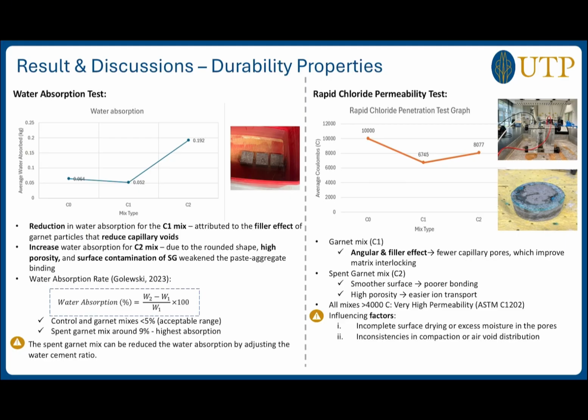The same trend was observed for RCPT, where the garnet mix has reduced chloride penetration compared to control concrete. It is because of the angular shape and filler effect, which can promote fewer capillary pores and improve matrix interlocking. And the spent garnet has increased chloride penetration because the smoother surface can lead to poor bonding, and it can make ions transfer easily. So, even though there is a reduction in chloride penetration for spent garnet and garnet mix, these two mixes are categorized under very high permeability because the charge passed is higher than 4,000 coulombs.